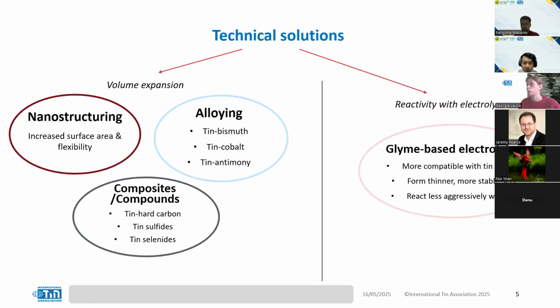So the question is, how can we overcome these challenges? There have been solutions developed, which is fantastic. If we look at the issue of volume expansion, some of the methods being used are nanostructuring, for example, which uses very tiny nanoparticles of tin, which, because they're so small, have a larger surface area and create a more flexible material. Because of this, they can better accommodate the volume expansion and avoid cracking.